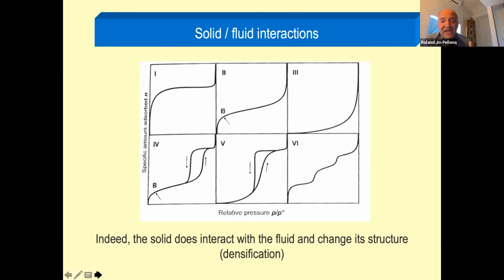But what is interesting is that this capillary condensation is not the bulk one, because it obviously occurs in relation to the bulk, but it's actually shifted towards lower pressure.